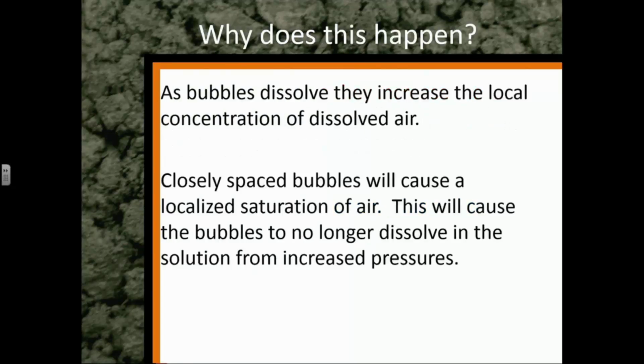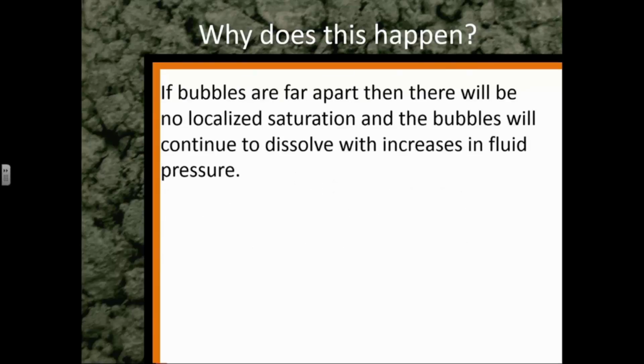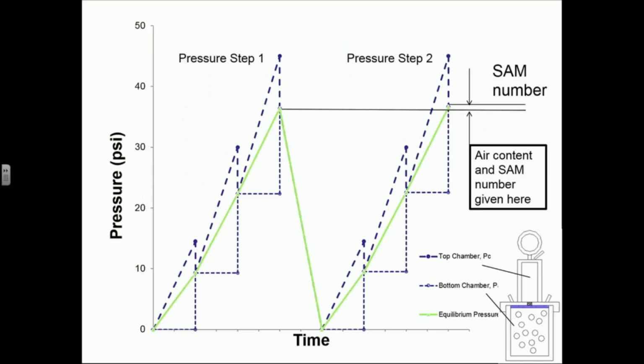But why does this happen? As the bubbles dissolve, they increase the local concentration of dissolved air. So closely spaced bubbles are going to cause a localized saturation of air around them. And this is going to cause the bubbles to no longer dissolve in the solution from the increased pressures. If the bubbles are far apart, then there will be no localized saturation, and the bubbles will continue to dissolve with increases in fluid pressure.